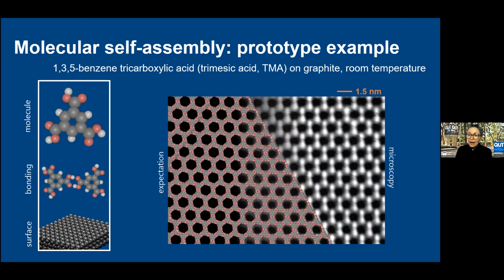acid. Because we can work on non-reactive surfaces, it means that we don't need to be in ultra-high vacuum to observe this structure. And this image I'm showing you here was actually obtained at the solution-solid interface. So it's a very nice technique because we can implement it in a bunch of different situations.